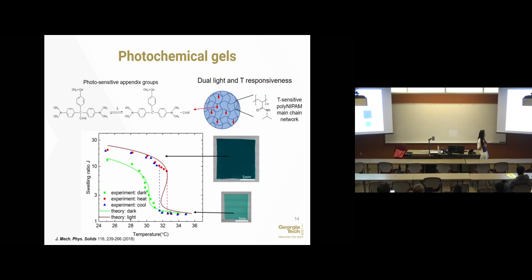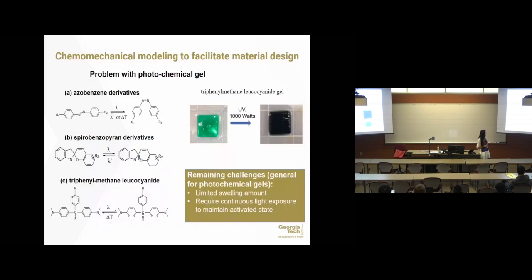And what is interesting is you can see, right, from this green curve to this red curve, the temperature shift is very small. So in operation, if you want to get a light responsiveness of the material, meaning when you shine light, it swells or shrinks dramatically, right? You have to operate in a very, very narrow temperature range. Here it is just about 1 or 1.5 degrees C. So without this quantitative tool, in a real experiment, it's very easy to miss this performance behavior.